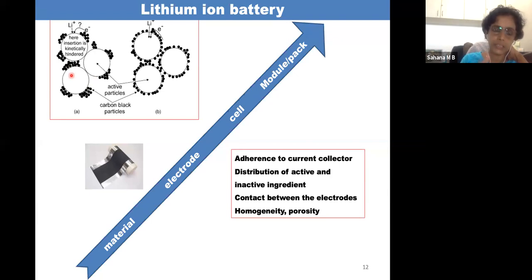So the conductivity of electrons as well as lithium ion should be good, and it should be accessible at a common point. Now here what happens, this is kinetically hindered. The empty space, which we call pores, is where the liquid electrolyte will come, whereas the electron will come only through the carbon black. So the conductivity from here to here is low. So this will not be a good architecture for a lithium electrode.